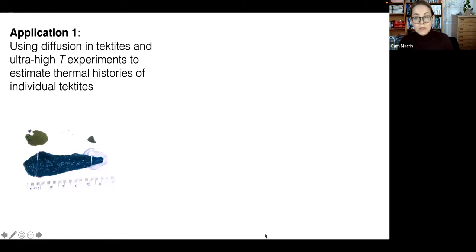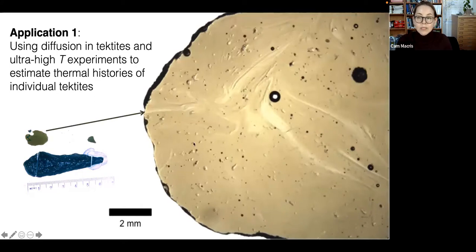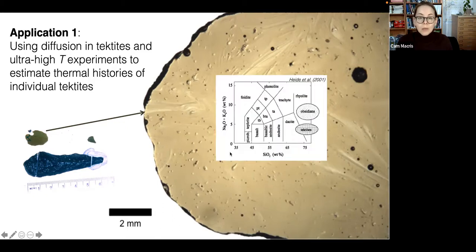But let's start with the first study, the diffusion study. Here I'm showing you a photo of an Australasian splash form tektite. It was cut into slabs. As you can see, this piece is missing here. That's this slab laid out above. And now I'm showing one of these slices or slabs magnified. This is just a transmitted light photomicrograph. The purpose here is that we can see some of its features. The majority of this glass is sort of beige brown in color. It has a roughly rhyolitic composition, as you can see on this plot of alkalis versus silica. So this is the rhyolite field, here's obsidian, and here our tektites plot. You can also see that the tektites are more depleted in alkalis than obsidian.